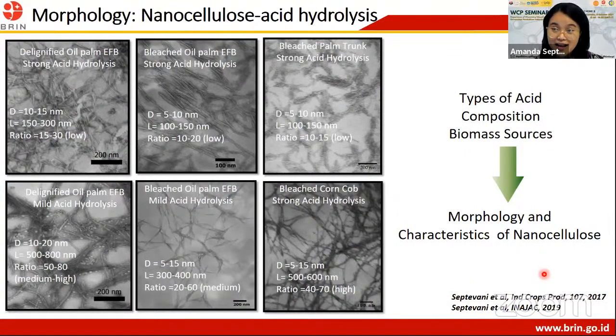So there are several approaches to produce nanocellulose. First is acid hydrolysis via the chemical approach. You can see this is the morphology of our cellulose after acid hydrolysis. From here, you can see that a rod-like shape of nanocellulose can be obtained from strong acid hydrolysis, while with mild acid hydrolysis, we can obtain long entangled cellulose nanofibrils. So usually, by using strong acid hydrolysis, we produce a low aspect ratio, meaning the ratio between the length and the diameter of the fibers is low. While if we use mild acid hydrolysis, we can get longer fibrils with a medium to high aspect ratio.